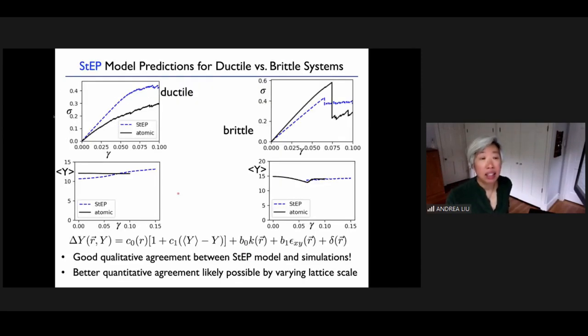So what do we get from this? The stress strain relation, here's for the ductile system, here's for the brittle system. These are now the simulations, we're comparing now to simulations from Miyazaki and Ozawa from Ludovic Berthier's group. This is not softness, right, because we're trying to predict local yield strain now. So we call it Y. It's a structural predictor of local yield strain. And this is the behavior of the average value versus strain in the ductile case and in the brittle case.